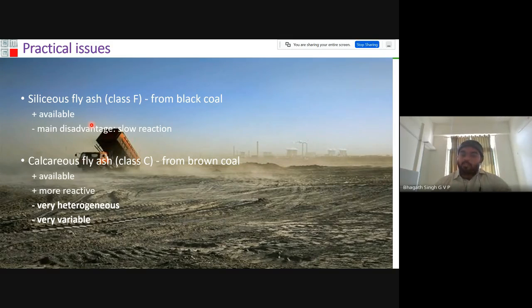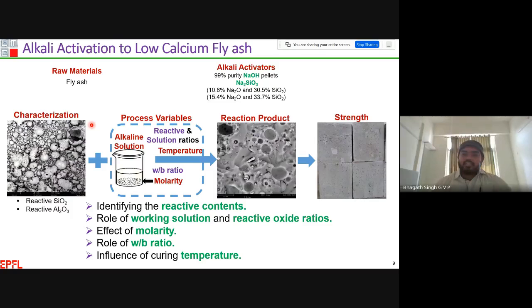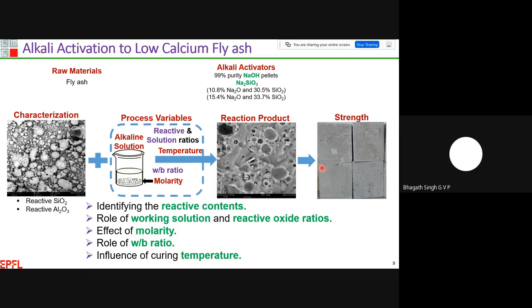And to overcome this problem, I have introduced a systematic approach to produce alkali activated low calcium fly ash based binders using the siliceous fly ash. And this is a schematic representation of how the compressive strength occurred in alkali activated fly ash. And here I have used sodium silicate and sodium hydroxide as the alkali activators to activate the fly ash.